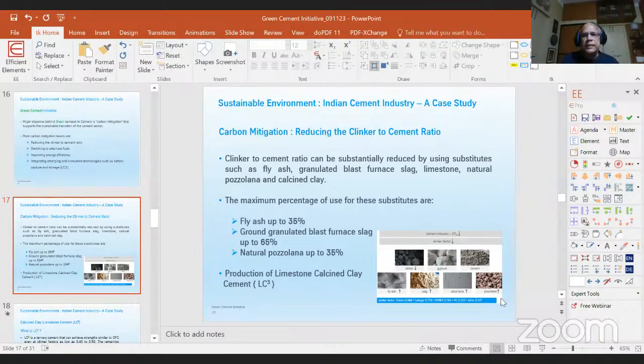Now there is something interesting here. The maximum percentage of use of these substitutes are, as per the Indian standard, the cement standards, fly ash you can add up to 35%, which directly will reduce the clinker component to almost 60%. Ground granulated blast furnace slag can go up to 65%.